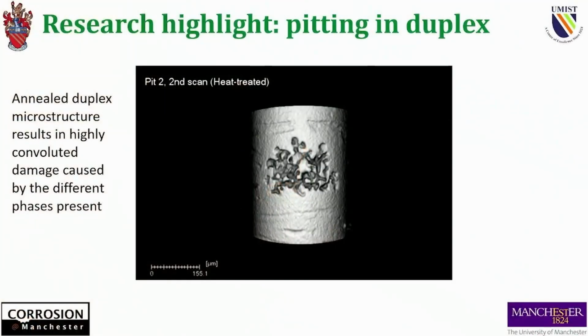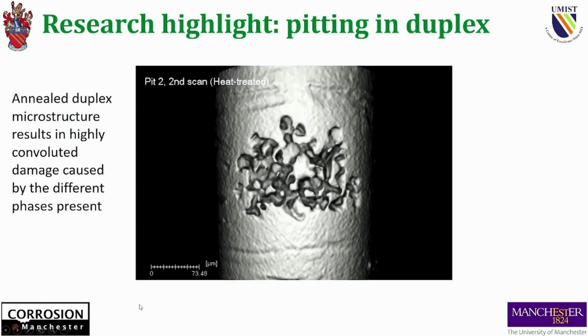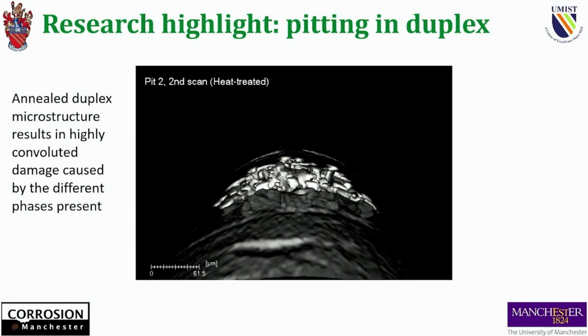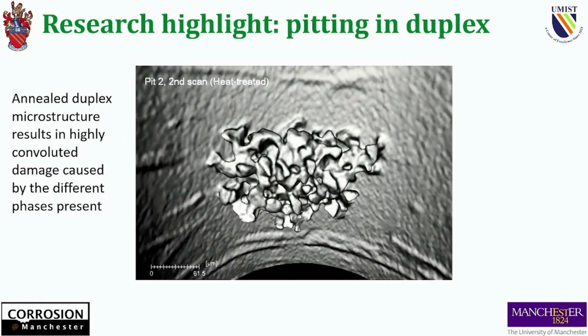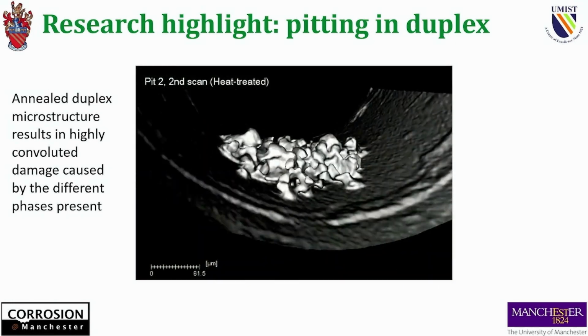Another one from Dirk. This is a tomography picture. So what we're looking at here is the annealed duplex microstructure. It corrodes in different ways because of the duplex structure where you have ferrites and austenites with different compositions. So this is a tomography picture, X-ray tomography. Another movie, and quite a lovely picture. That's what the pit looks like on the outside. And we've always wondered what pits look like on the inside. Well, there we go. We can now tell.